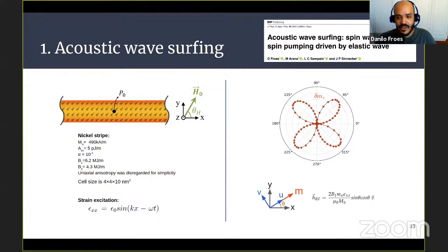The first thing we did was check if the simulations were working by changing the direction of the magnetization, doing this excitation, and measuring the amplitude of the spin wave that's formed there. So here's a polar plot of it when we have the magnetization parallel or perpendicular to the k.